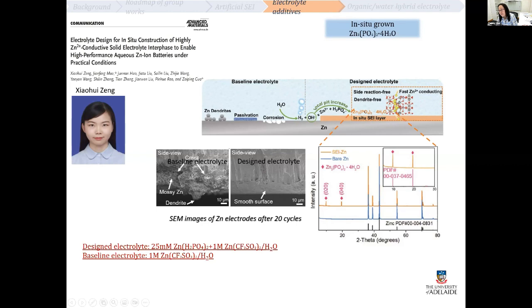So this zinc phosphate is a fast zinc conducting compound, which helps to facilitate zinc diffusion. From the XRD, we can clearly see this peak corresponding to this SEI, indicating it successfully formed on the surface. And after 20 cycles, from the zinc anode cross-section view, we can see the zinc deposition is dense and smooth, while in the bare zinc anode, you can see the mossy shape of the